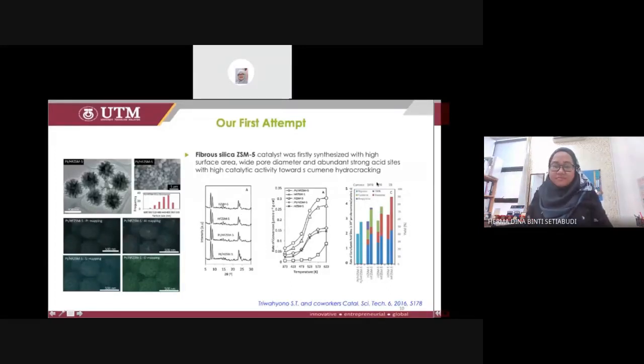And then we tried on the cumene cracking. As you can see here, this is the rate when we use the fibrous silica ZSM5. The rate is the highest one. And you can see here, the higher one in all results is for the fibrous ZSM5 compared to the conventional one. The red one is the benzene, so cumene cracks to benzene. This is a very successful result for us, which we reported in Catalysis Science and Technology in 2016.